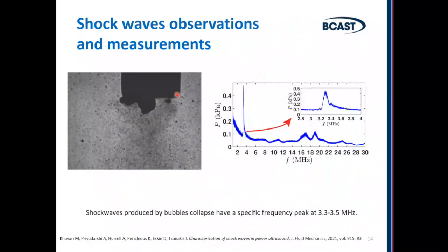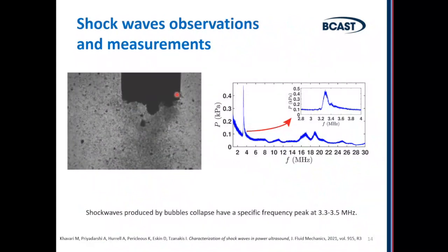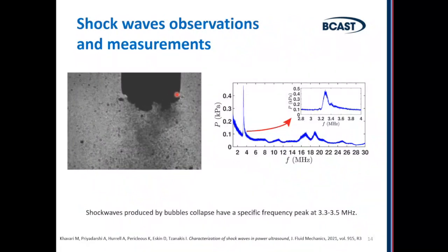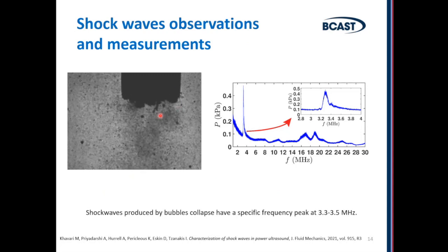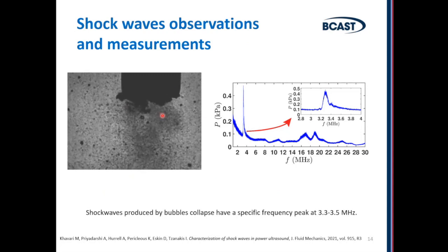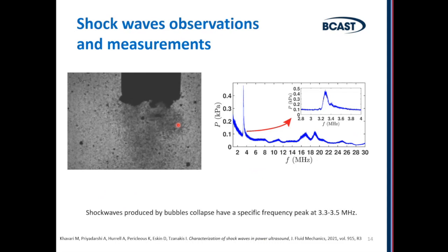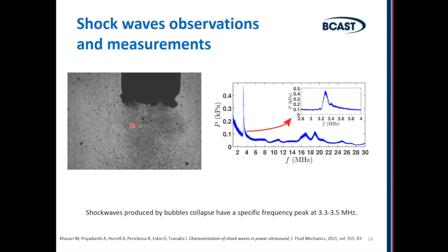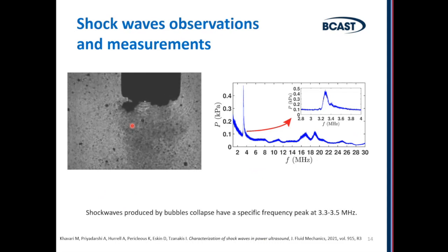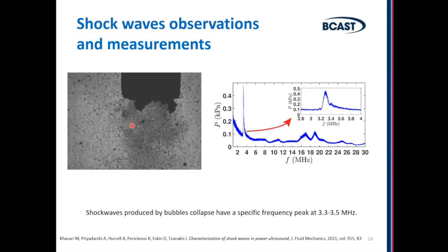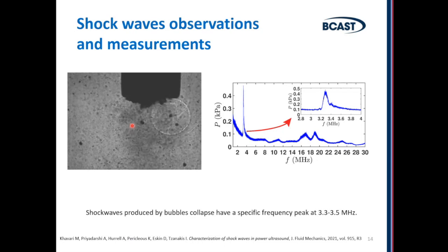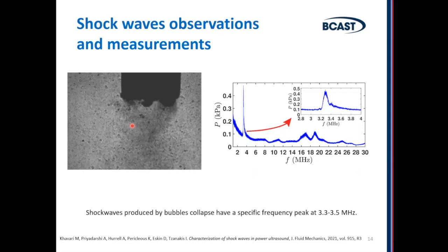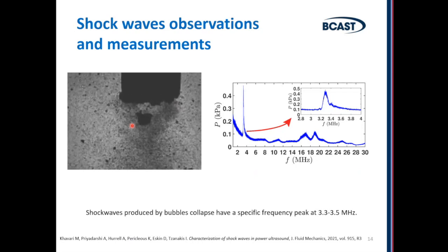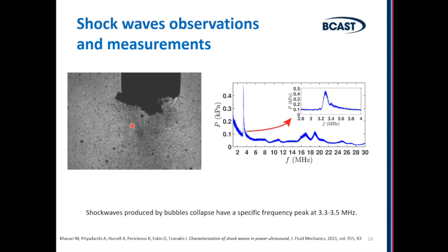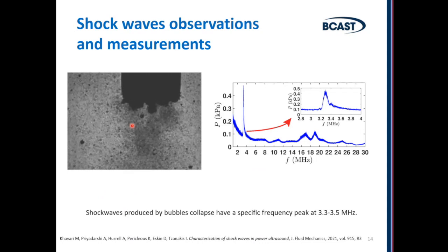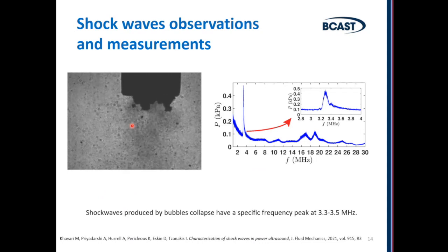When cavitation bubbles collapse, or the cloud of bubbles collapses, they produce shock waves. And nowadays we can also visualize the shock waves. You can see these semicircles appearing, which are actually pressure shock waves emitted by a collapse of bubbles or a cloud of bubbles. And we can also measure acoustic characteristics of the shock waves, and they are believed to be responsible for a lot of mechanical effects induced by cavitation processing of liquids.